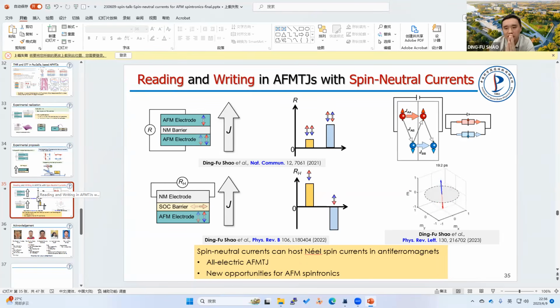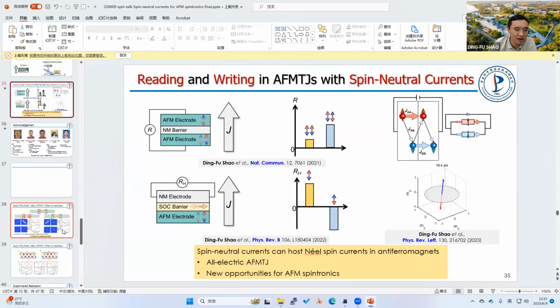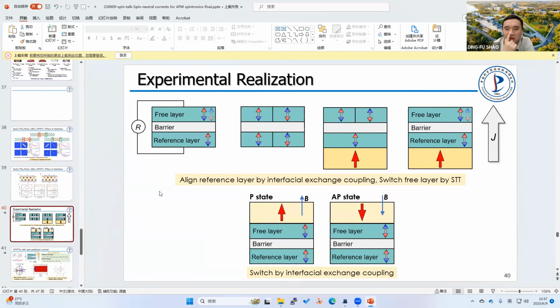So far in the experimental reports, people do not do specific treatment to control the domain alignments or Néel vector alignments, but it has been observed that we can have some spin current generated, which means we do not have perfectly compensated domains. So I believe if we directly deposit the ruthenium oxide, we can have some of the effects I predicted. Maybe it is not strong. I generated some supplemental pages here.